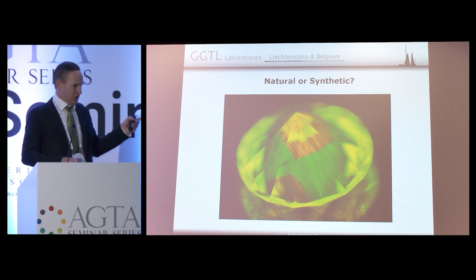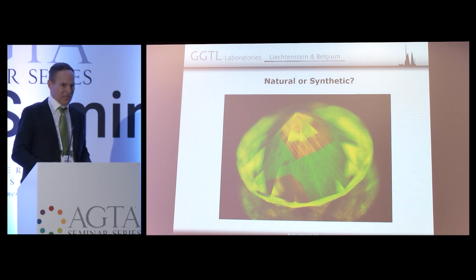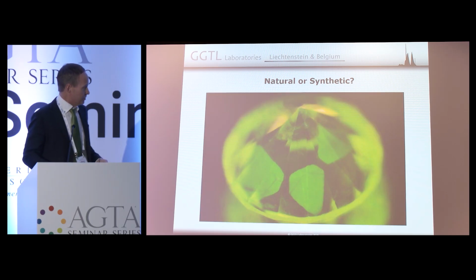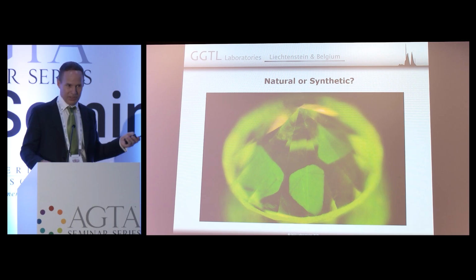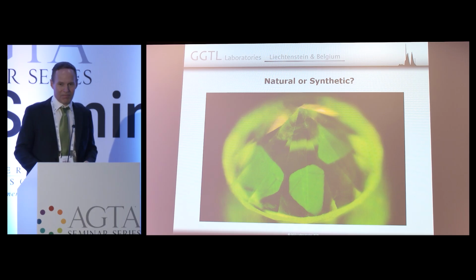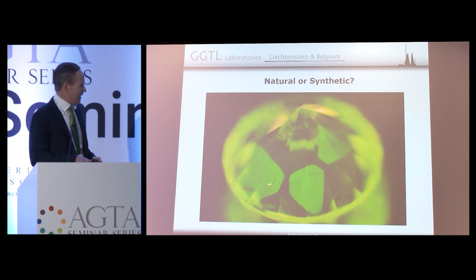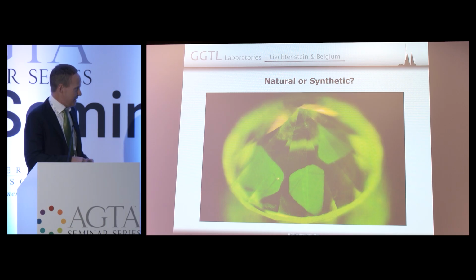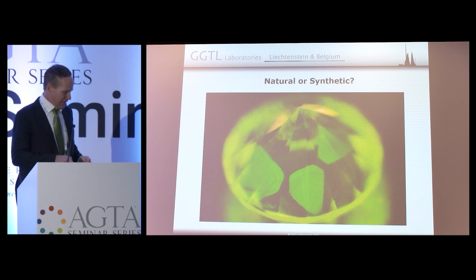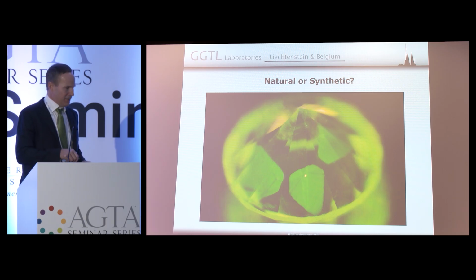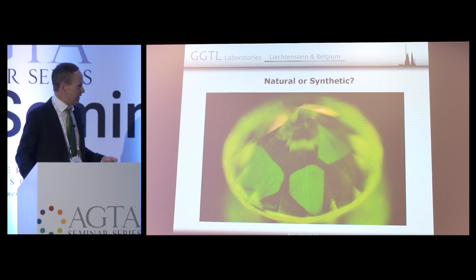I mean, sometimes I show a few more now. Sometimes you're like, wow, this looks synthetic, but sometimes it takes more than just the fluorescence image. But here, for example, guess on this one. Natural. Another one. So here what gives it away are actually these features here. You can see these lines here. That gives away that this is just a mixed growth diamond that developed these interesting sectors. They're a little different than what you see in a synthetic, but this can be really disturbing when you see it. But again, this is just exceptional. These stones, we see a couple of them once in a while, so it's not very common.